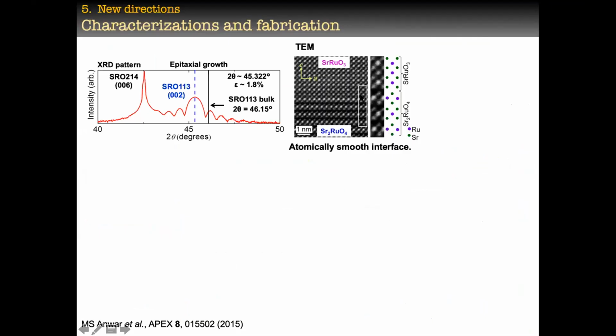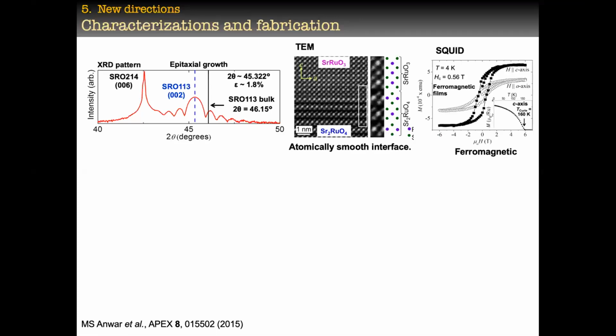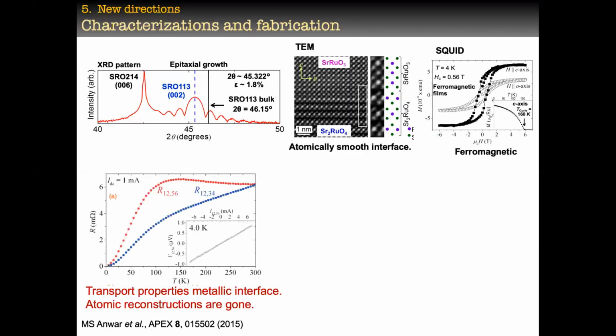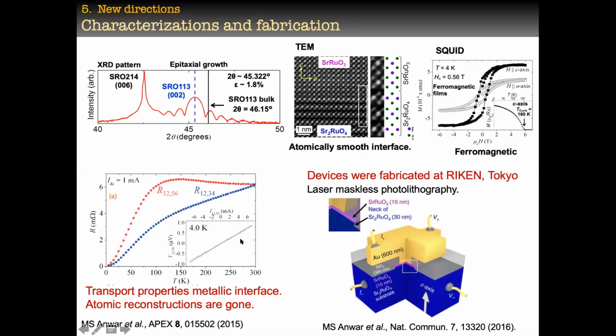And now you have to look at the interface under the transmission electron microscope, and you see this is atomically smooth, and it's beautiful actually, the interface. So material is ready to go ahead, and then we need to check the magnetization, whether it is also ferromagnetic. Yes, it is. Wow. And it is a ferromagnet, and the interface is metallic, and the resistance is going down with decreasing temperature, and it's a linear ohmic interface. So now ready for the device fabrication.